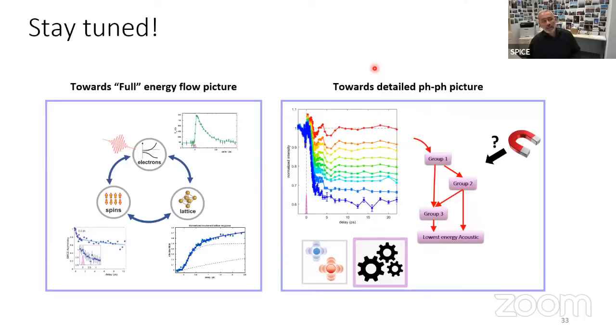Now, you can write, if most of the effects are coming from interband transitions without a strong contribution from side-jump scattering, which tends to be only a small correction, or skew scattering, which tends to be for very, very high conductivities, in the DC limit that's going to be connected to this Berry curvature integrated over the whole phase space, which can be translated to these interband transitions with these dipole matrix elements. Once you go to finite frequency, essentially you're modifying your denominator. Instead of dividing by the difference in energy, it is the difference in energy plus the frequency that is involved in the transition, but it's still connected in that sense.